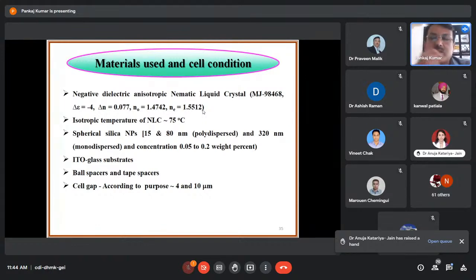Here the concentration used was 0.05 to 0.2%. Here the concentration is less as compared to the previous one. ITO glass substrate we have used, ball spacer and tape spacer both were used for the experimentation, and cell gap according to the purpose, 4 micrometer as well as 10 micrometer, we have used.